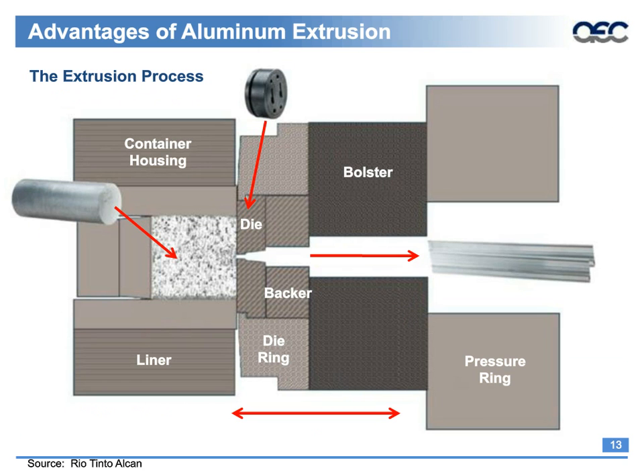So again, the aluminum extrusion process starts with an aluminum billet, which is pushed and compressed by the dummy block and the press, the stem, which is to the left of that first arrow, and then it goes through a die, and all of this other material, the backer, the die ring, the bolster, the pressure ring, and ultimately the press that it's sitting within, really keeps that die from bending. That's terrifically important because these presses are many millions of pounds, or 2,500-ton press, so 5 million pounds or 10 million pounds of pressure being put on these steel dies, so they do need to be properly supported.